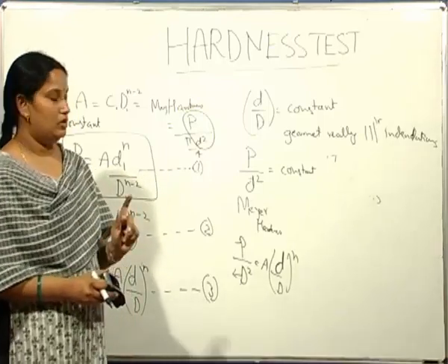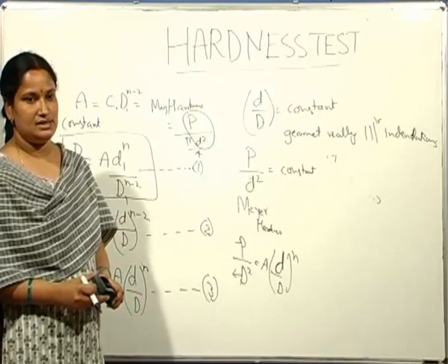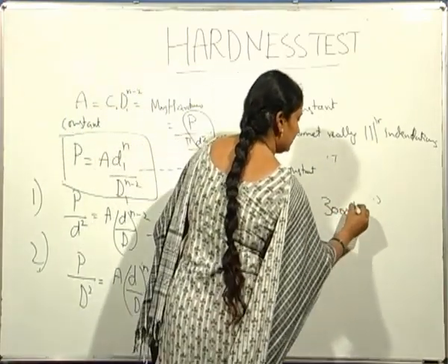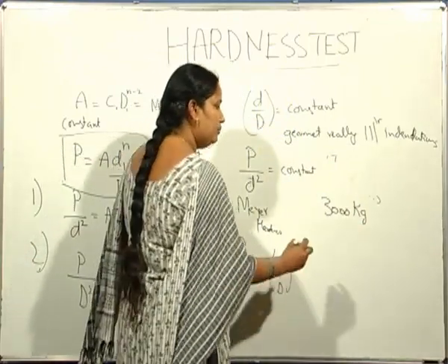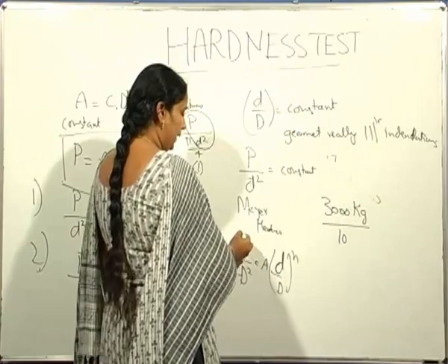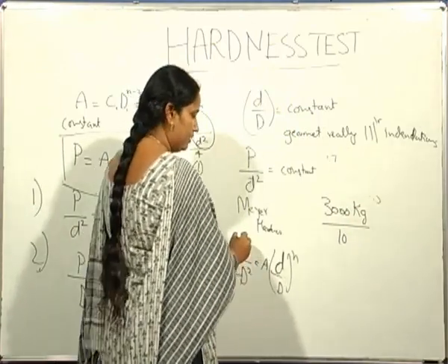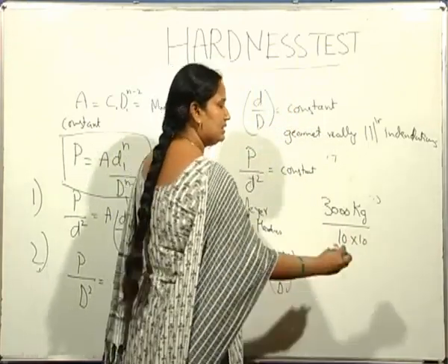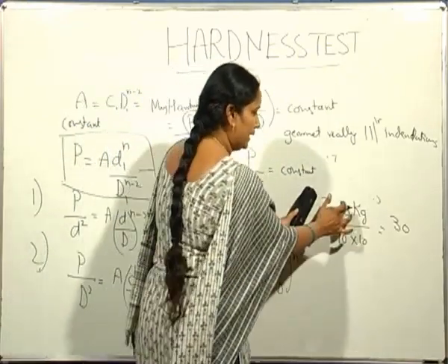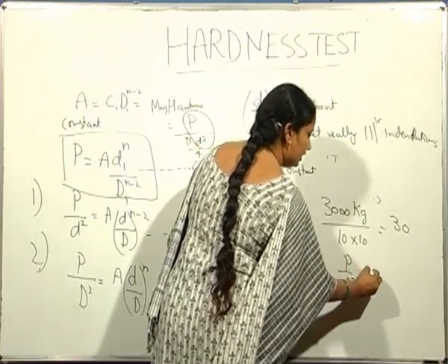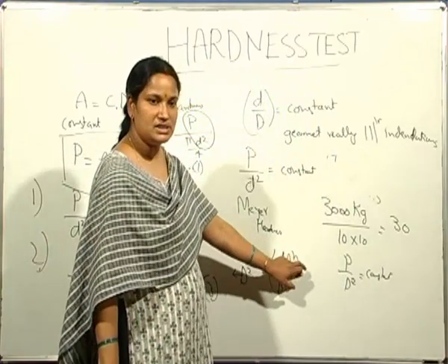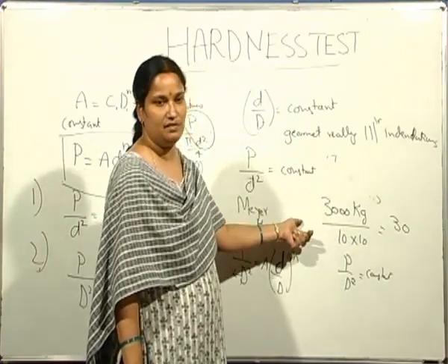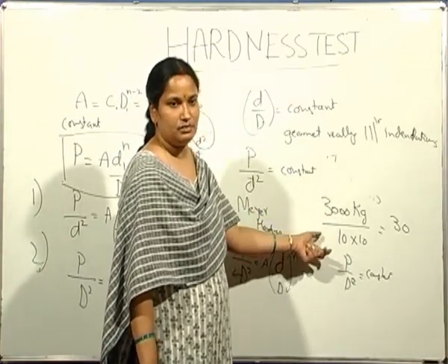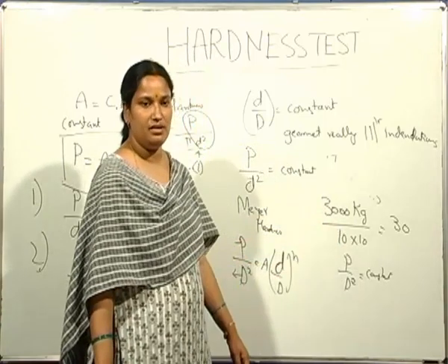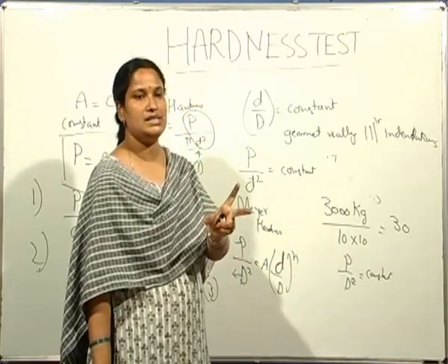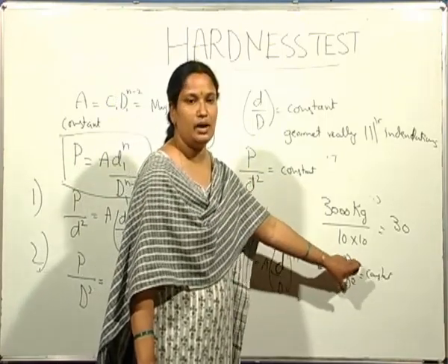I'll give you one example. For the case of Brinell hardness test, if a load of 3000 kg is used and the diameter of indenter is 10, P by D square, according to this equation, is 3000 by 10 into 10, which is equal to 30. So by maintaining P by D square equal to constant, even though one uses a non-standard load which is different from the standard value, or a non-standard indenter which has a different diameter than 10, one can obtain the same hardness value by maintaining this ratio as constant.